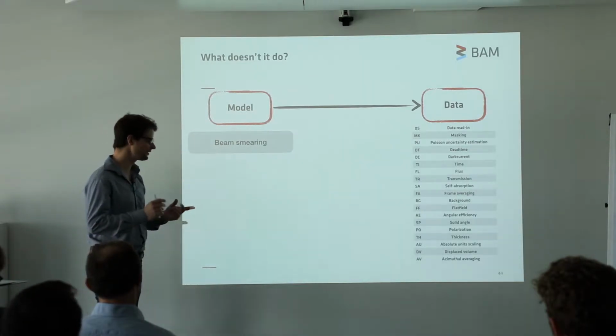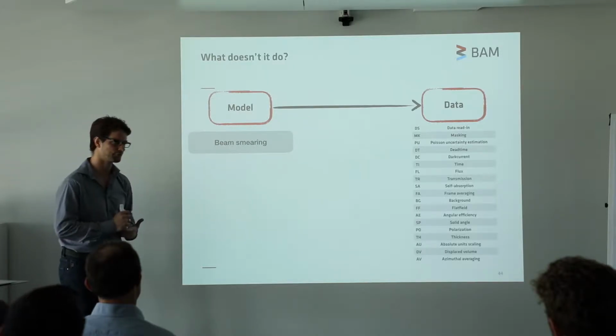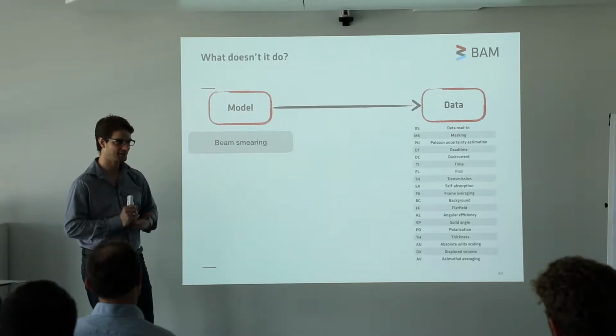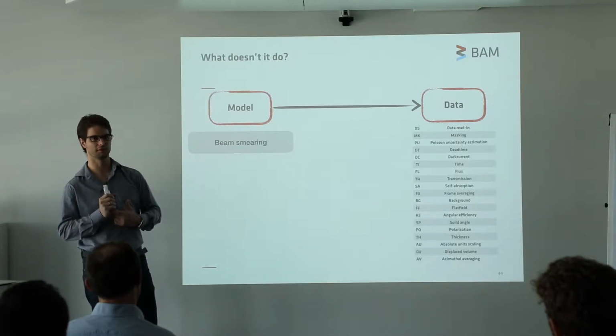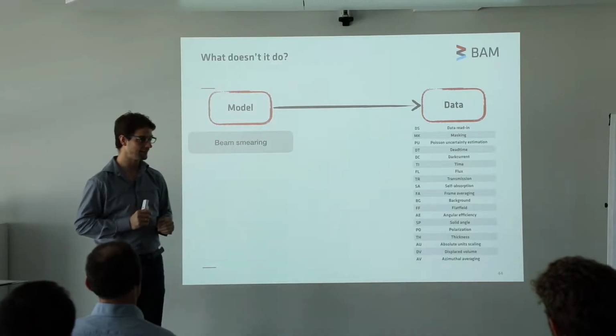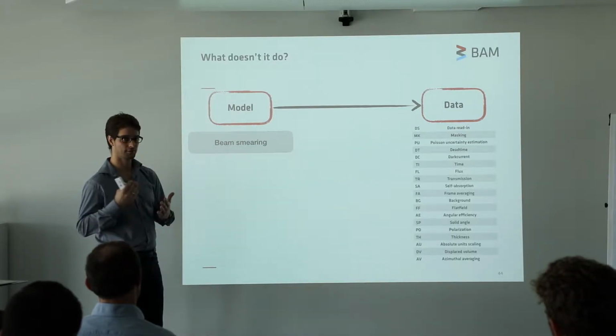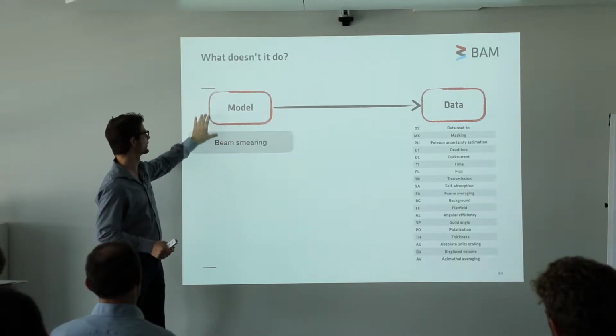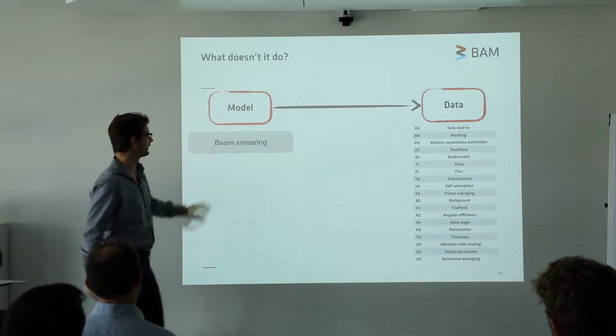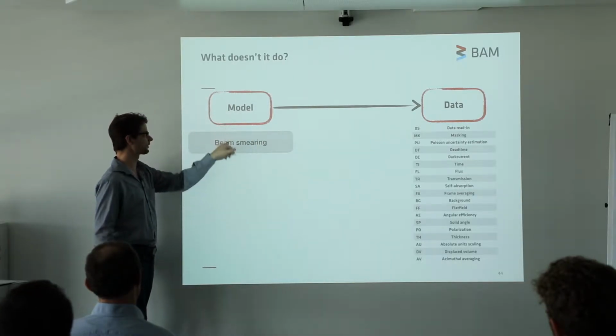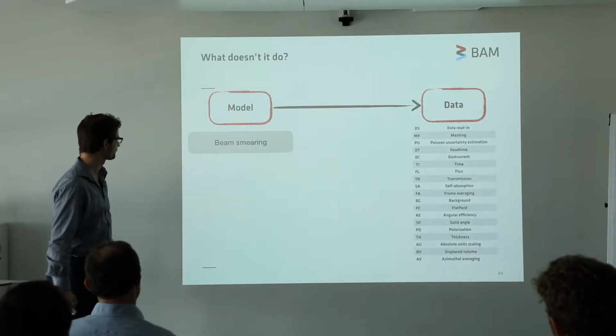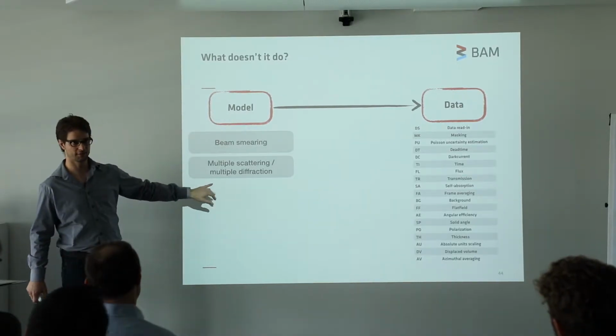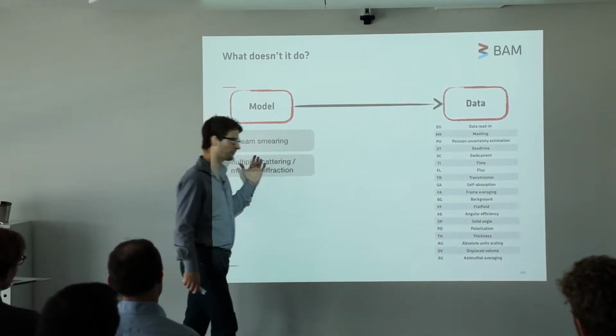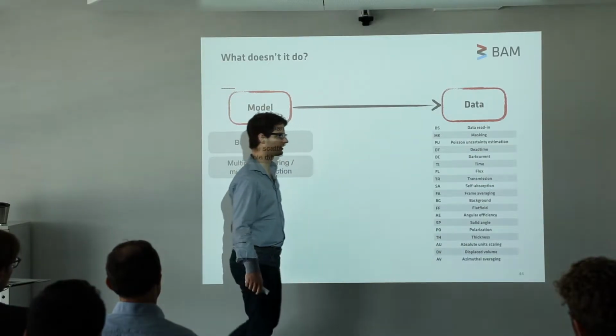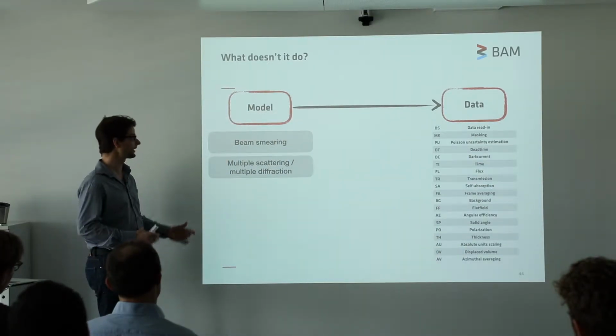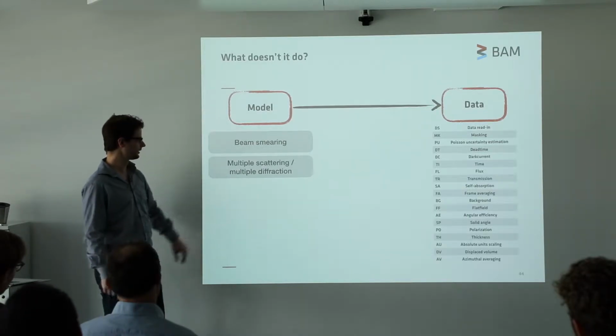And some do, but this is a mathematically ill-posed problem, and it is a risky thing to try because you will increase your uncertainty estimates, and you may introduce artifacts into your data. It is, however, much safer to take the beam smearing into account in your model, and thereby improve the match between the two, because here it's just a convolution of the model with a known beam profile. Same goes for multiple scattering, multiple diffraction. We might be able to indicate whether this is an issue during the data correction step, but we can't or we won't correct for it. You can calculate this much better in the model itself.